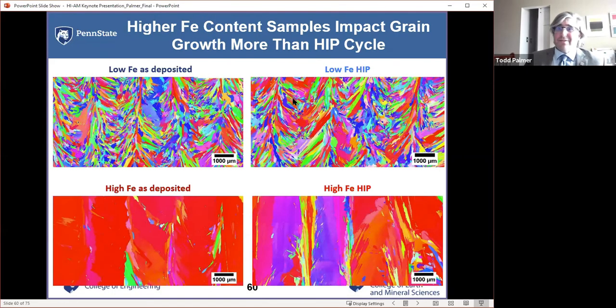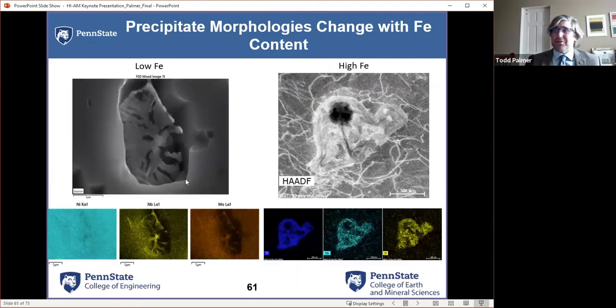Now, how did this dictate itself? It came out as significantly different grain structures, low iron versus high iron. We had this huge growth in the grain structures of our high iron. The other thing it did was we saw about a 25% difference in yield strength. Putting that together, I've got materials that are nominally supposed to be the same specification-wise, with a 25% difference in yield strength. I've got some issues I need to work my way through here.